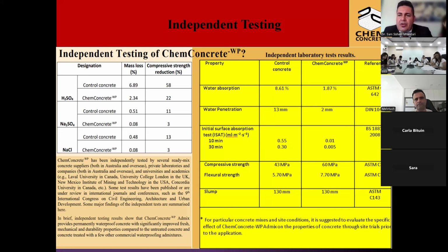And some of the test results have already been published in international conferences or journals. In brief, all the independent test results that we have received so far, those companies have also reported and received similar results as what we have reported in our technical data sheets. So they have further proved the effectiveness of the product. Here in the left table, you can see the acid, sulfate, and chloride resistance of control concrete compared to concrete containing our admixture. And in the right table, you can see the water absorption, water penetration, and some other concrete properties.